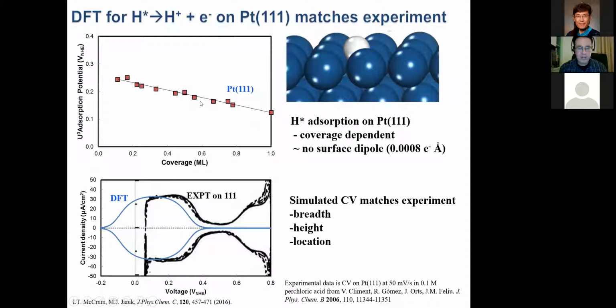As the coverage goes down, it gets harder and harder to take the hydrogen off. And I have to then make the surface more and more positively charged to drive that high coverage off as protons. And then finally, I'll get all the hydrogen off. And that's the black experimental curve. And this is our model. Our model says when you started that experiment, you didn't have a whole monolayer of hydrogen. You were already down to about 0.8 of a monolayer. And then it came off as you did the experiment.